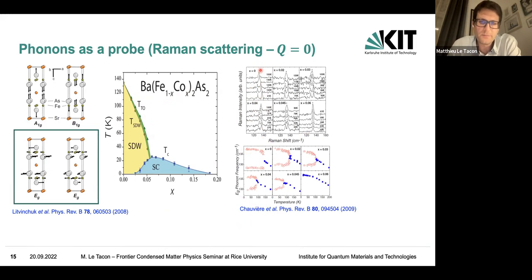And what they see here in the signal is the in-plane polarized mode, so the Eg mode. When you're in the tetragonal phase, the Eg modes are completely degenerate because the vibration of the iron or arsenic atoms in the plane have the same energy if they vibrate along a or along b, essentially. So this is doubly degenerate. And then when there is the formation of the spin density wave, and the orthorhombic distortion associated with it, you split the mode, you lift the degeneracy between the two Eg modes, and you end up with a B2g and a B3g mode in the orthorhombic phase.